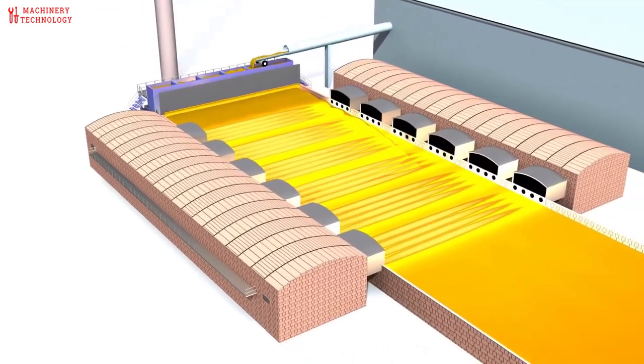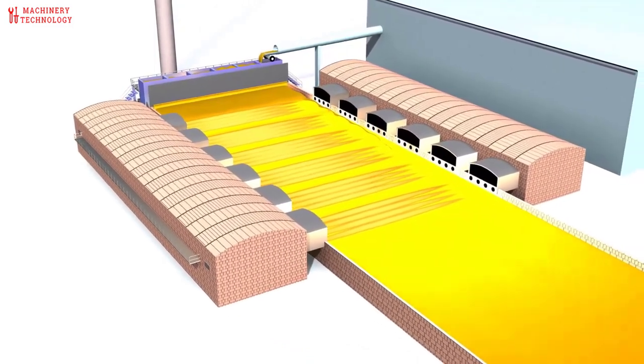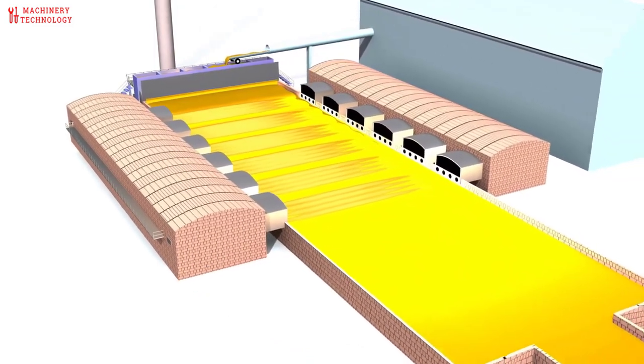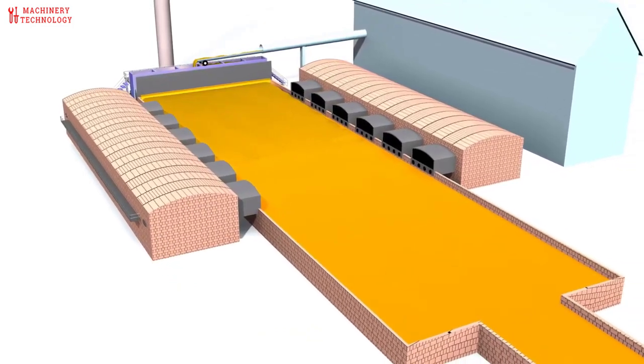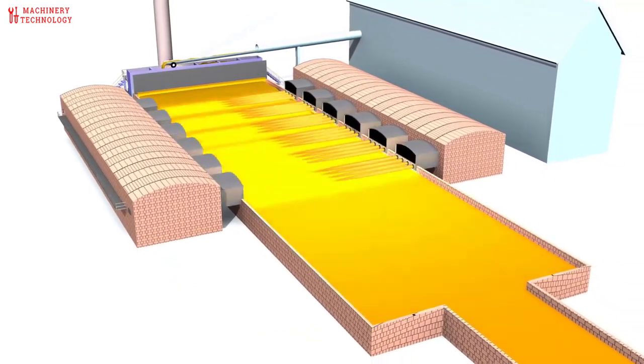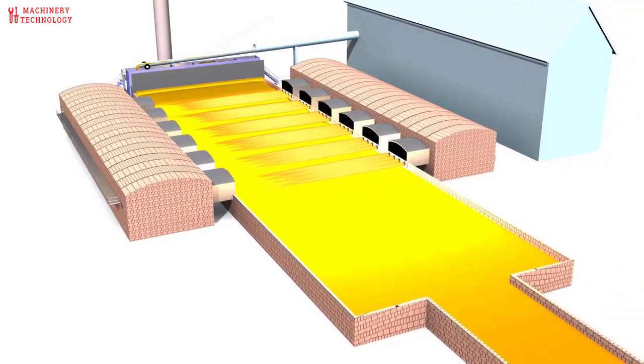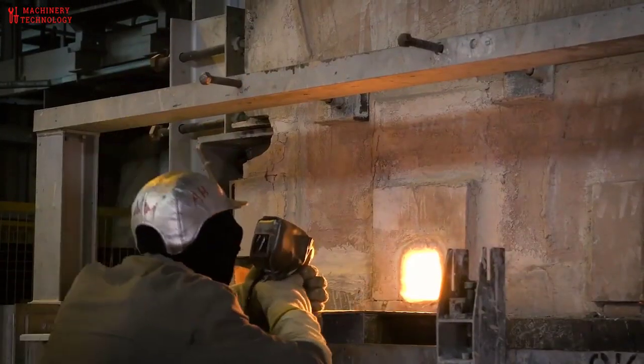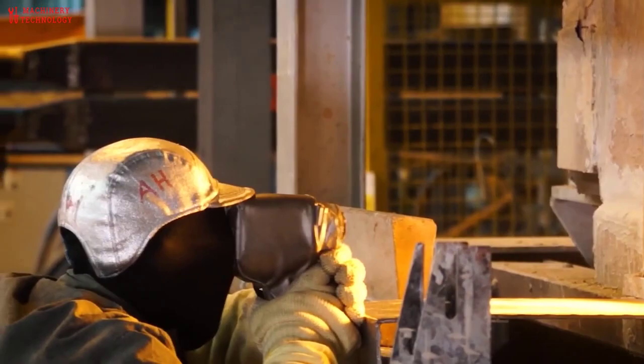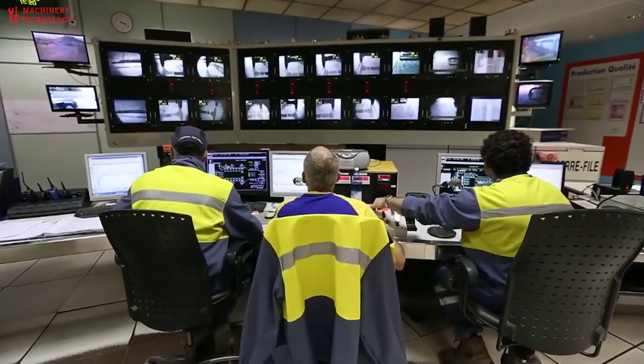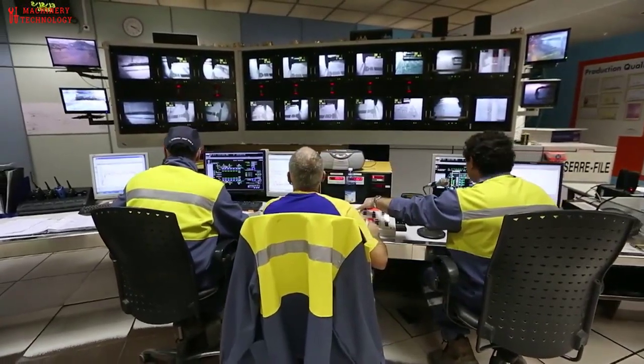Melting occurs by heat transfer from the flames located above the glass surface. Chemical reactions between the different elements allow the elaboration of high-quality glass free of bubbles. The process within the furnace is continually monitored by technicians who take measurements inside and from screens in the control room. The flames develop above the furnace. Every 20 minutes, their direction is reversed to optimize the thermal balance in the furnace and the efficiency of the flue gases heat recovery chambers.